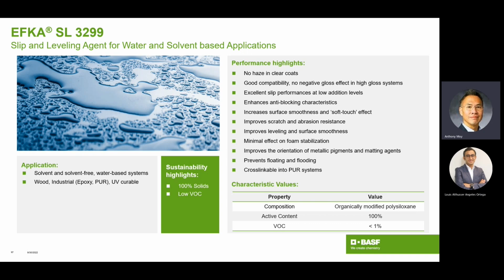It will actually lower the surface energy at the surface of the coating and give you an anti-block type of performance effect. Anti-block is the situation where you put a coating on two pieces and then you stack or lay those pieces on top of one another. And later on, you're going to want to remove those pieces. And when you do, you would like for the coating to be intact and not sticking to itself and peeling off of one part. Well, that is exactly what EFKA SL 3299 is designed for. It can provide you with that anti-block performance.